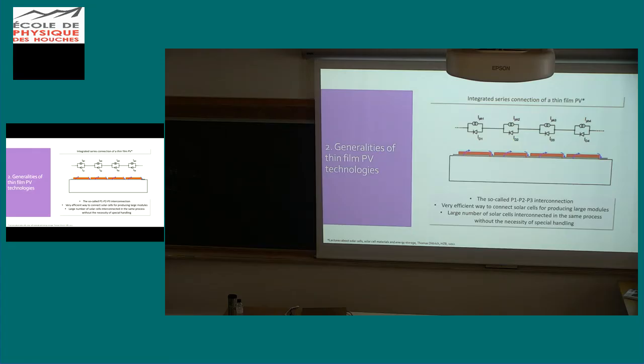Another advantage of thin film photovoltaic technology is that, of course, you cannot produce a single cell of 1 square meter. It's impossible because the series resistance of your metallic layers and of the TCO you need to connect will kill your device. So for that, people invented some time ago this series interconnection, normally called the P1, P2, P3 interconnection. Basically it's a strategy to design very thin cells of 1 centimeter or 2 centimeters width maximum, very long, 1 meter can be, and then interconnect them in series. Then you have an increase in the voltage, you are adding the voltage, and you keep the current constant among all of them.